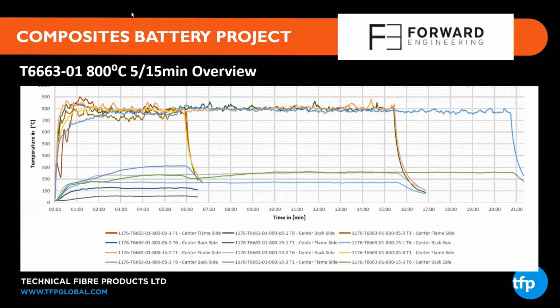You can see some of the experiments are stopped at 5 minutes, some at 15 minutes, and some of the experiments allowed to run on to 20 minutes. And if you look at the lines towards the bottom of the graph, you can see that we're seeing temperatures really between 150 and 250 degrees centigrade on the back face of the laminate. We're seeing insulation values of 550 to 650 degrees centigrade for incorporation of the Technofire intumescent veils.